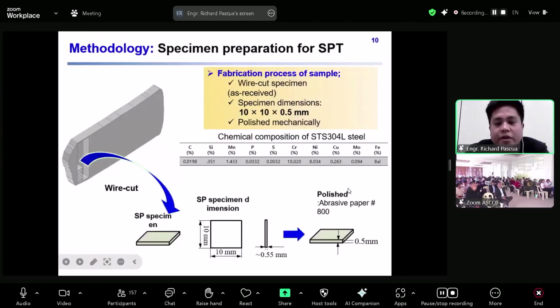For the specimen preparation, our samples are made by a wire cut process with the corresponding dimensions, and we manually polish one side surface of the specimen using abrasive paper to remove impurities before exposing it to the hydrogen environment.